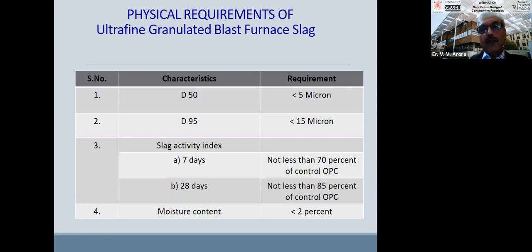Physical requirements for ultrafine slags are these: D50, that is the diameter for 50% of the material, should be less than 5 microns, and 95% of the material should have a diameter less than 15 microns. So this is a very fine material. Slag activity index is also mentioned in this. So this material was being manufactured already, but the specification was missing. So now the specification is also there. So usage of this is increasing day by day.